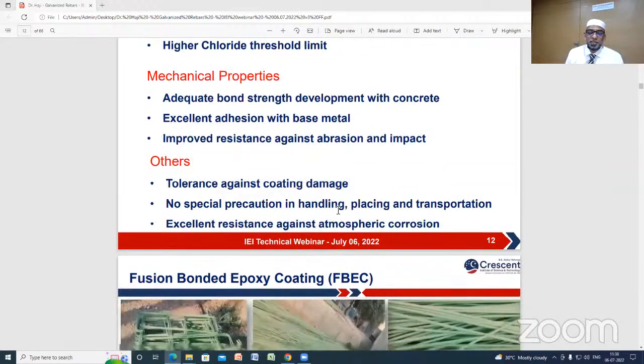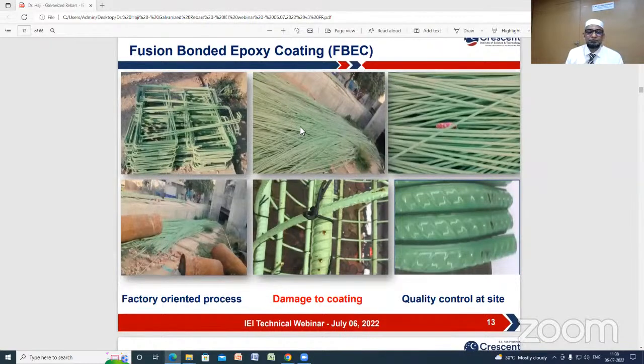I'll show you some of the photographs taken at site. This is fusion bonded epoxy coated rebar used in a construction site in Chennai. Actually, government is spending so many crores of rupees as a prevention strategy, but due to poor construction practices on site, poor handling, even before the concreting, the coating is disturbed and pitting corrosion is happening. So we have to be very careful. If we are going for prevention strategies, we have to stack the rebars as per the manufacturer's guidelines.